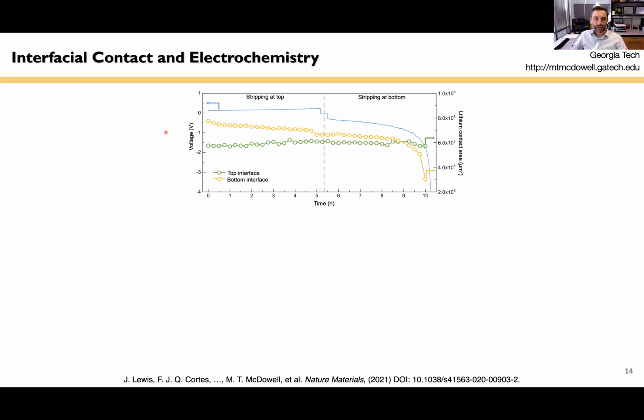So here in this plot, we're mapping out the voltage curves of the cells. So here's stripping at the top interface and then stripping at the bottom interface. And we're also plotting the overall contact area at the bottom interface and also at the top interface in green. So there's two interfaces. We have two sets of contact areas. And so we're mapping this out with time at both interfaces.